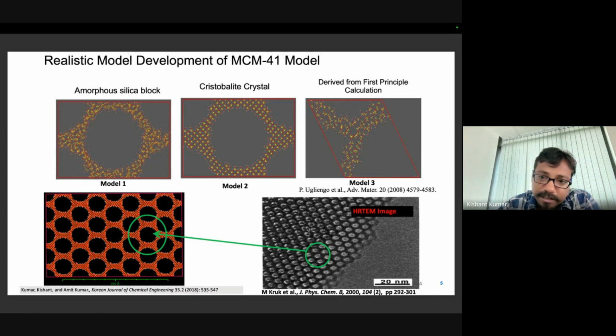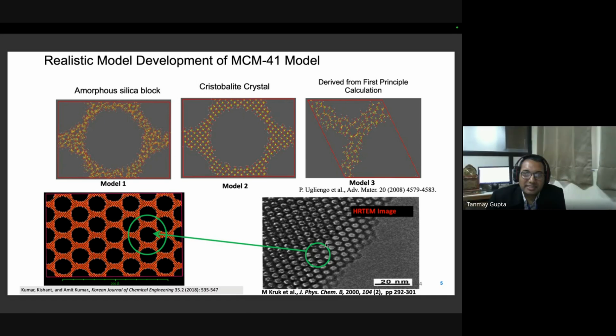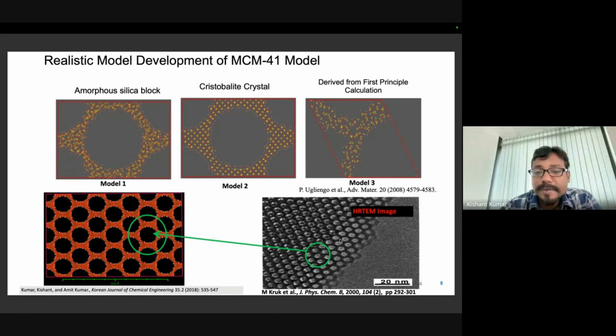Can you see my cursor here? Yes, sir, we are able to see your cursor. So this is the real experiment, a TEM image of the real experiment. So you can see here the pores are arrayed in a honeycomb structure. One pore is surrounded by 6 pores, you can see over here.